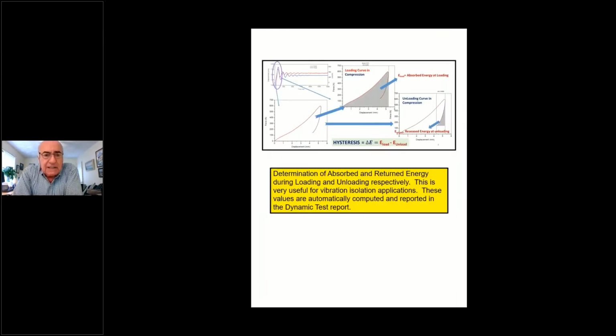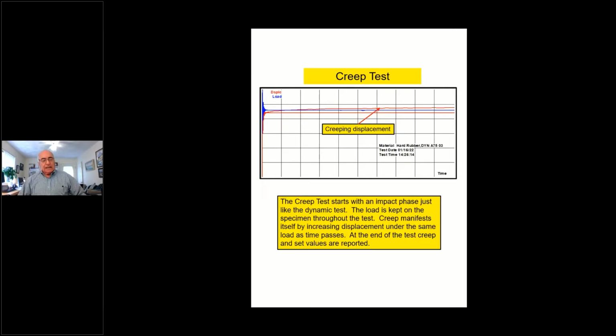We go to the next slide. Here we have, as you can see, a loading curve in compression and showing an absorbed energy at loading. And then released energy at unloading. And hysteresis is the difference, of course. And as the material is more elastic, then that difference is much less. If it is more plastic or more damping, the difference is quite high. Last but not least, creep test.